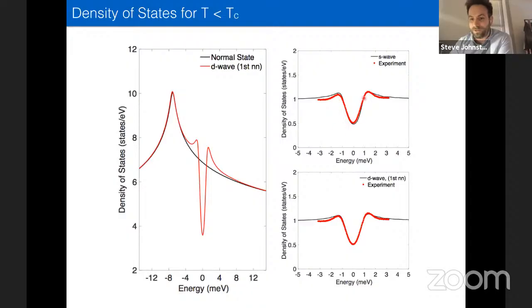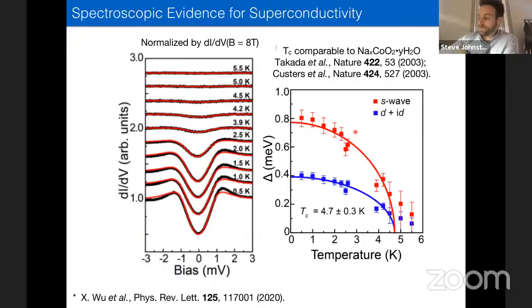You can see it here from the width of these peaks and the relatively small value of the gap. It's only about 1 meV. So it's quite challenging to get it from fitting the STS data. We can't get any reliable indication of what the pairing symmetry is. And so we needed to look at other means to identify it. I will say again, we can fit it as a function of temperature, again using multiple pairing symmetries.